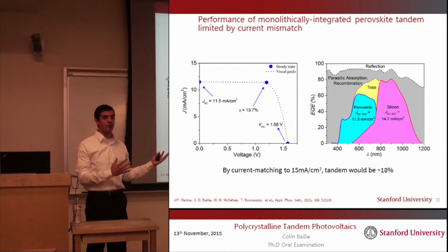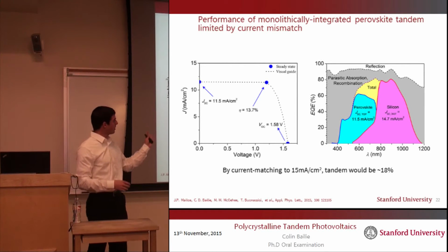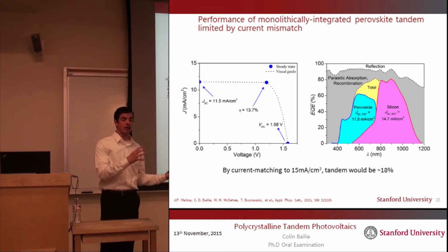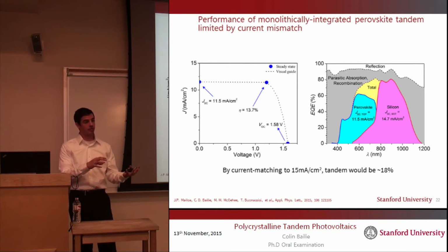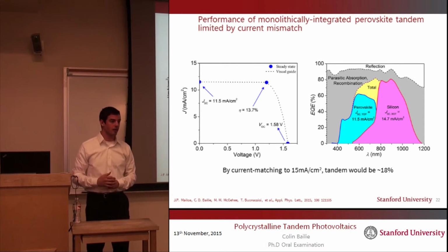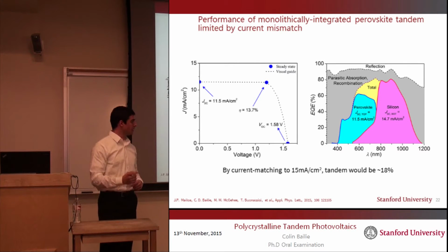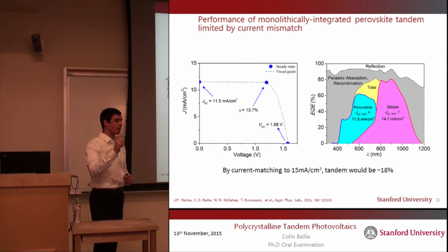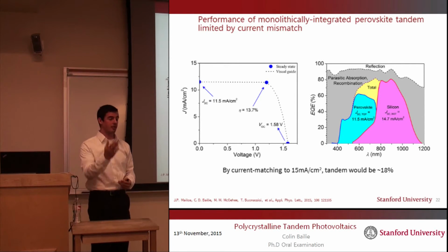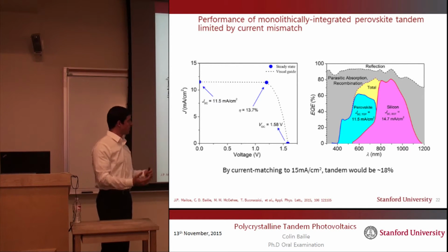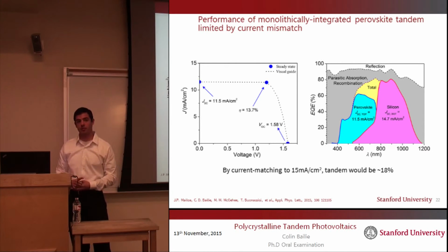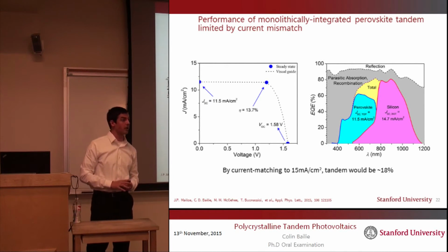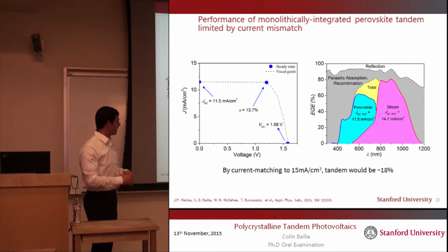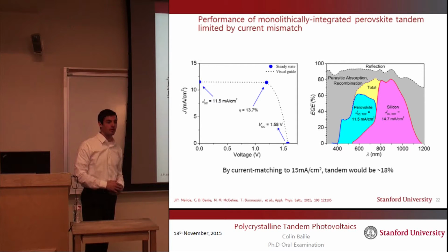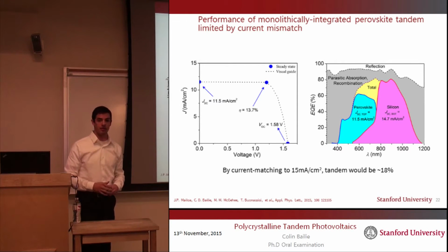This solar cell was ultimately limited in its photocurrent, and this is because on the right, the perovskite was generating 11.5 milliamps per centimeter squared in that subcell, and the silicon was generating 14.7. When you're making a monolithic tandem, there is a condition that you built into it that the top and bottom cells are connected in series, which means their voltages add, but also that you're restricted to having the same current pass through both cells. And so even though the silicon was trying to generate more current than the perovskite, that current was basically thrown away. And so, just speaking hypothetically, if we had managed to current match to 15 milliamps per square centimeter, we would have had about an 18% tandem.